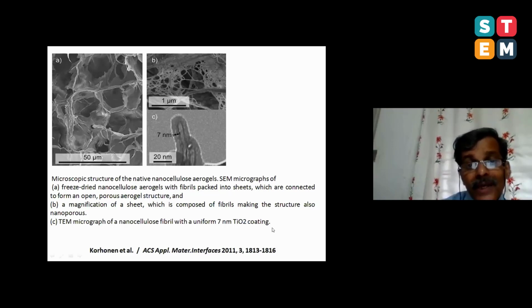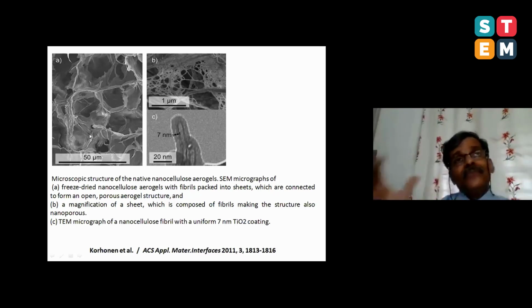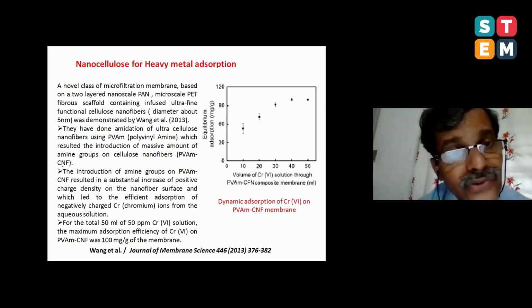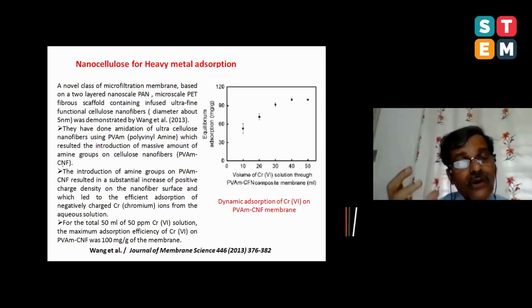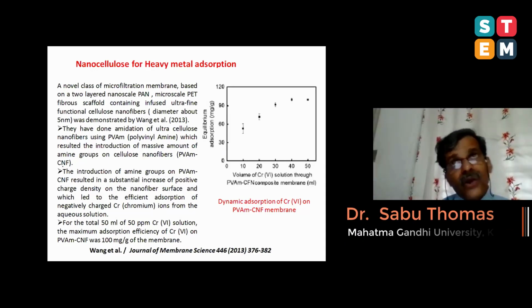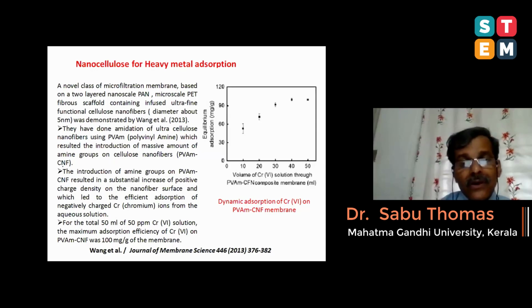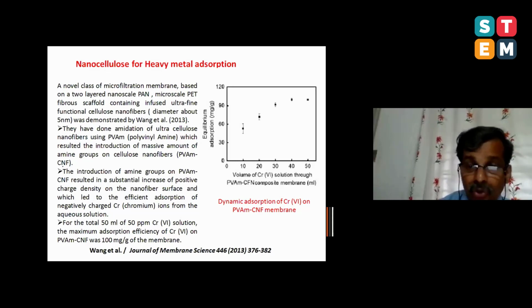Look at the chemical modification of nanocellulose by titanium coating. If you give a TiO2 coating on the nanocellulose surface, the surface becomes extremely hydrophobic. And this is extremely light and highly porous. Let me show you another slide where you can make use of nanocellulose made from waste for the removal of heavy metals like chromium.